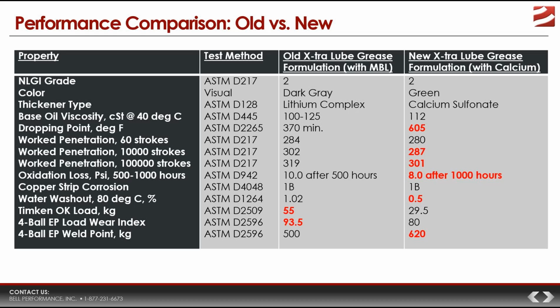Now, for the first time, the old X-tra Lube Grease performs better on that test. It has a 55 kilogram result versus 29.5 for the new grease. So we've had 4 essential properties where the new grease pretty much blew the old one out of the water, but then all of a sudden we're seeing that the old grease, at least on the Timken test, seems to be protecting better. Well, on that test alone, yes, but we also have the 4-ball EP test to consider, and if we understand the kind of results that go on this, we start to flesh this picture out a little more.